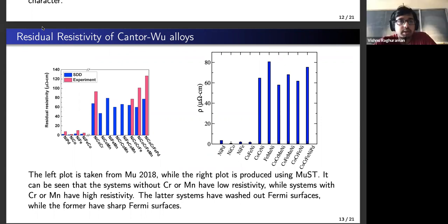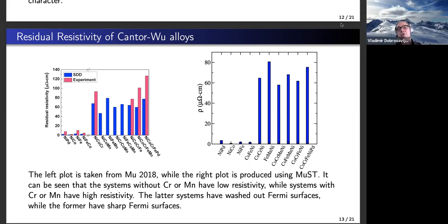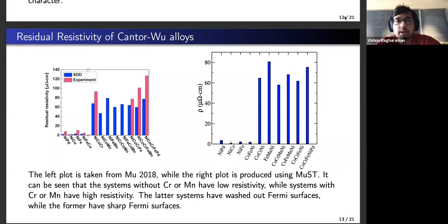Yeah, because generally when you put elements together, some of them strongly spin up and some spin down, then you see that effect. But in these first four elements, all of these elements are mostly spin up, and you see a very high conductivity along one spin channel. But usually the magnetism is temperature dependent. And how is the resistivity responding to the changes of magnetism? Or some of them may not actually be magnetically ordered like that. Yeah, I think these calculations are all at 0 Kelvin.